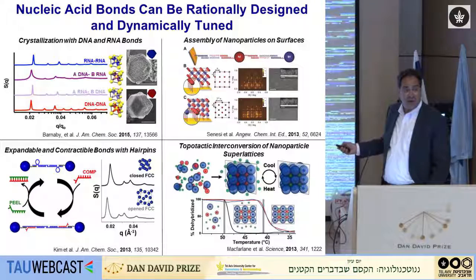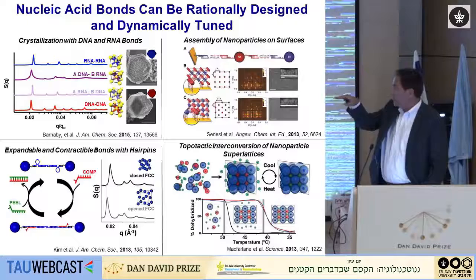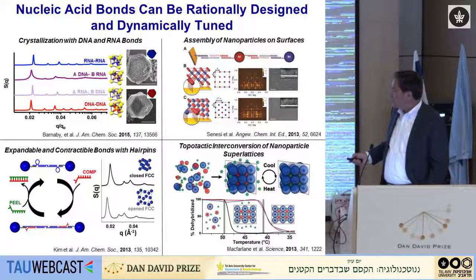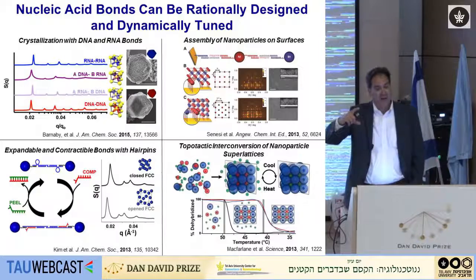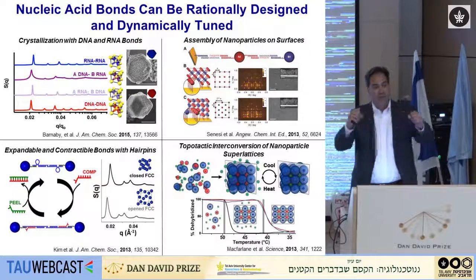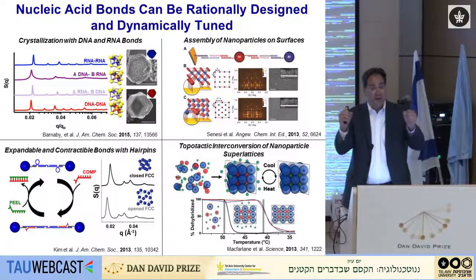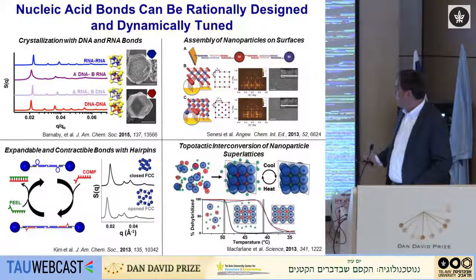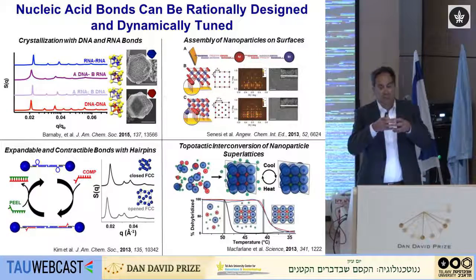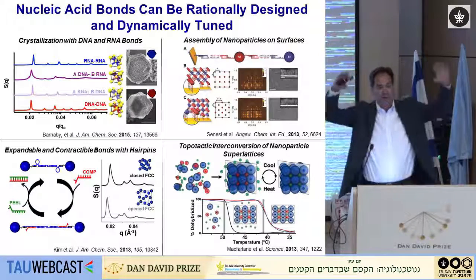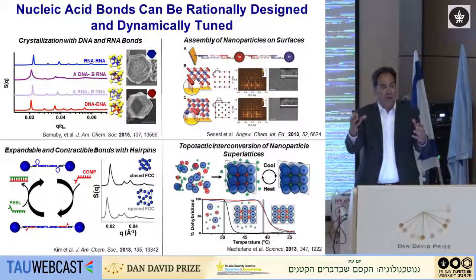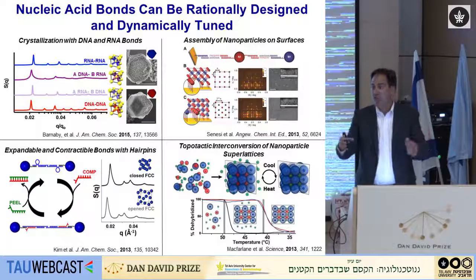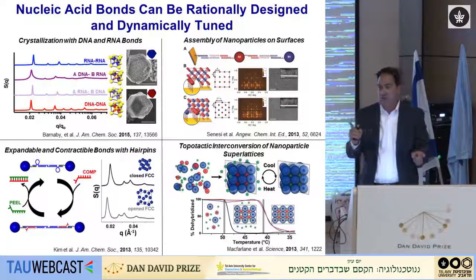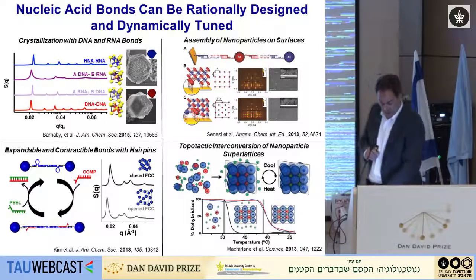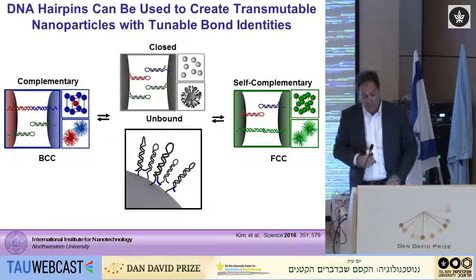This is our version of epitaxy, where I make one perfect layer, a second layer, a third layer, and a fourth layer. I can build structures like the one shown here, where I have hairpins that allow me to have expandable and contractible bonds, so I can move the particles apart and bring them back together, controlling the interactions between the particles. And you can do what we call topotactic interconversion, where we can take one set of particles and assemble them into one lattice, let's say a binary structure where we have two different components, and take a third component that can go in and bond to different oligonucleotides within that existing lattice to transform it into a new type of architecture. And so this ability to interconvert matter becomes, I think, really quite interesting and potentially quite important. And that kind of takes me to the next concept.